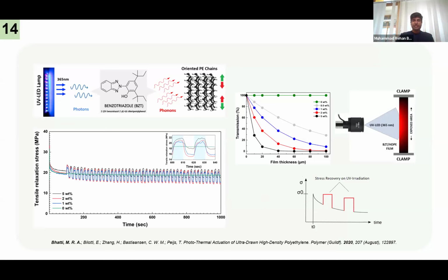At that point, we expected that the actuation performance of oriented polyethylene can be enhanced through increased draw ratio, because we believe that the effect that we are getting, the actuation stress, is actually the multiplication of two things, which are the Young's modulus and the negative coefficient of thermal expansion. So if we increase the chain orientation, we will be able to increase the Young's modulus, and so the actuation stress.